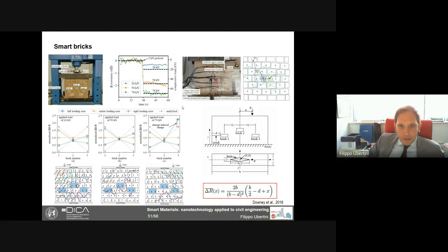But then at 70 kilonewton, we have a crack forming in the wall. And in fact, we have a large deviation of brick number 3 with respect to what we read in the previous steps of the test. So for sure, we have something sensitive to the load and we have something sensitive to the damage.